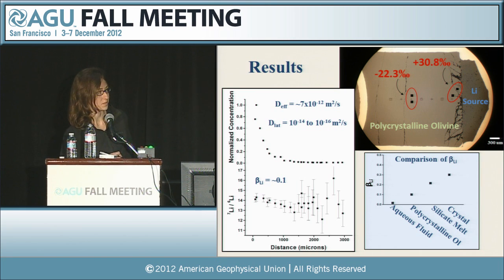So this is compared to diffusion of lithium in a single crystal of olivine by the vacancy mechanism, which gives values about 10 to the negative 14 to 10 to the negative 16 meters squared per second. On the bottom graph here, we have the 7 lithium to 6 lithium ratio, again, plotted as a function of distance. And these are our quadrupole results, so the errors are about 2 sigma, and they're quite large, but nevertheless, you can see a decrease in the values until it jumps back up to the background concentration of the olivine.